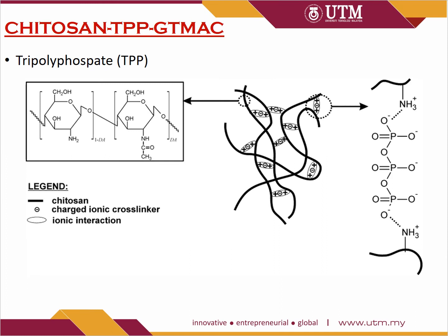Cross-linking reactions are required to modify the functional groups on chitosan and to increase the number of active groups of chitosan. Ionotropic gelation of chitosan by polyanions, particularly by tripolyphosphate TPP, a non-toxic polyanion that can interact with chitosan via electrostatic force to form ionic crosslink networks, has been widely used. Ionically cross-linked chitosan hydrogels can be used as a drug delivery system for controlled release not only in acidic but also in basic media for rapid release by dissolution and as a thermogelling system.